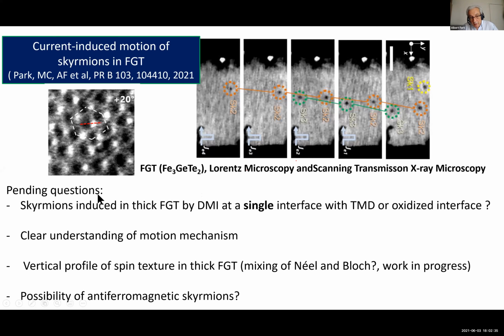For example, there are several pending questions in this system, as well as in the FGT experiments at UCLA. It is difficult to understand because these FGT are not single layer. They have something like 30 or 40 layers of FGT. And so it's difficult to understand how skyrmion DMI can be induced by interfacial effects at a single interface, with a transition metal dichalcogenide at UCLA or by oxidation in our work at a top interface. So this problem has to be solved.